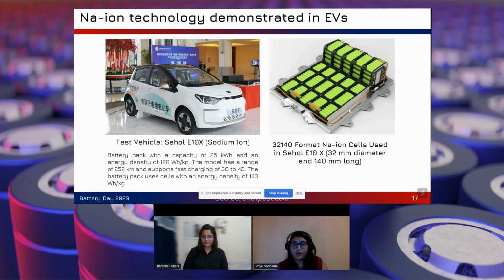Okay. Another question we have from Derek: what is the current path forward in improving sodium ion batteries cycle life? What are your thoughts on that? Yes, that's a very good question. Right now, mostly the cathode materials that are being used, which are showing a good cycle life, are polyanionic and Prussian white, which have a very stable structure. And these can easily intercalate and de-intercalate sodium ions into their structures. But if we talk about the oxide-based cathodes, which have a higher specific capacity compared to polyanionic and Prussian white cathodes, these oxide-based cathodes face challenges of structural integrity during long-term cycling.